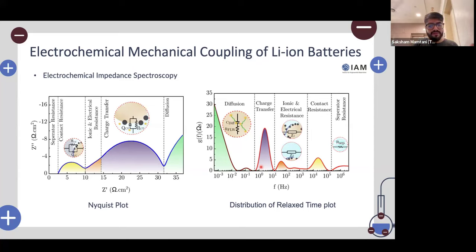So if you see a Nyquist plot, which has two very prominent peaks and then a more or less linear kind of increase, this particular element accounts for the diffusion. The biggest peak is usually for the charge transfer. We have ionic and electrical resistance as the initial part of the peak. And then we have a small peak, which might contribute to the contact resistance. And this is one way in which you can analyze the output of spectroscopy.